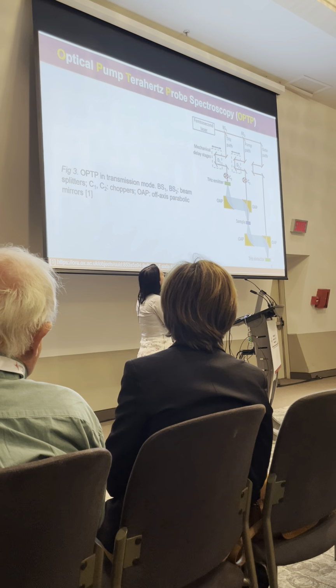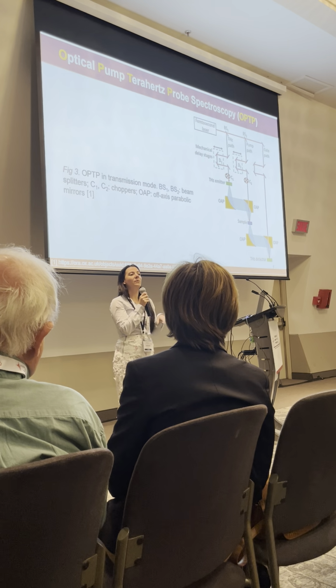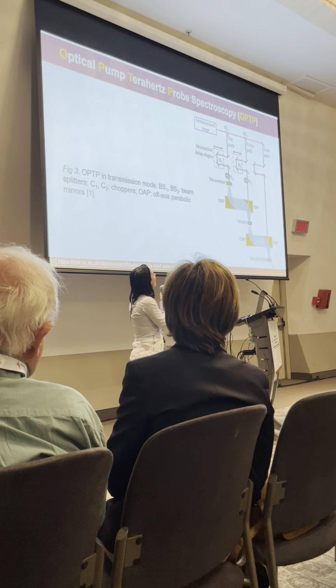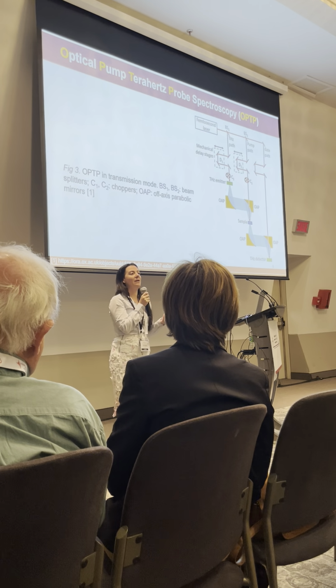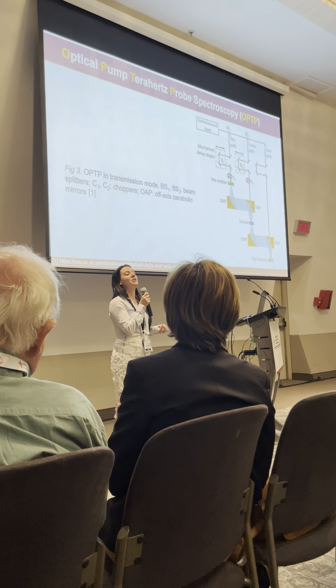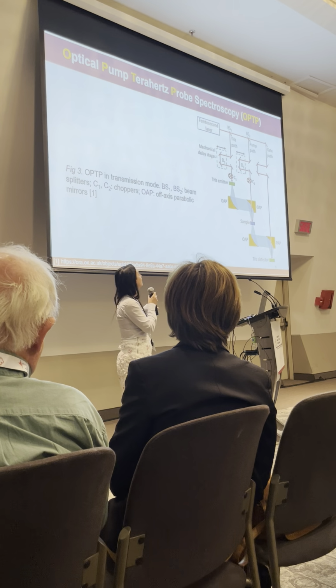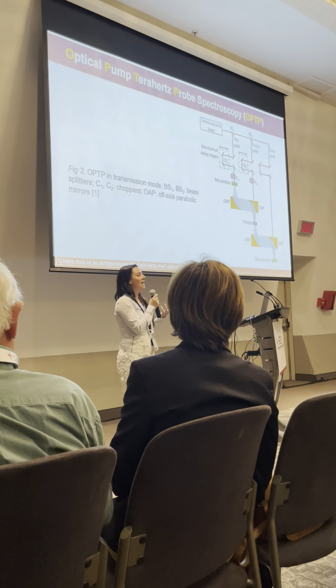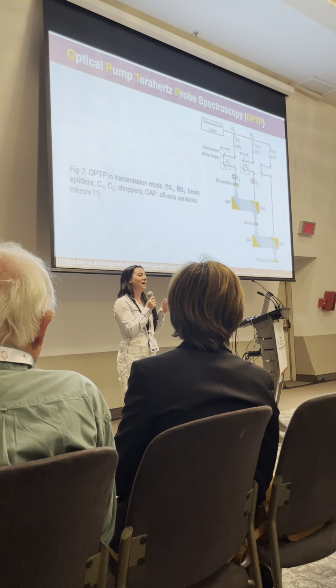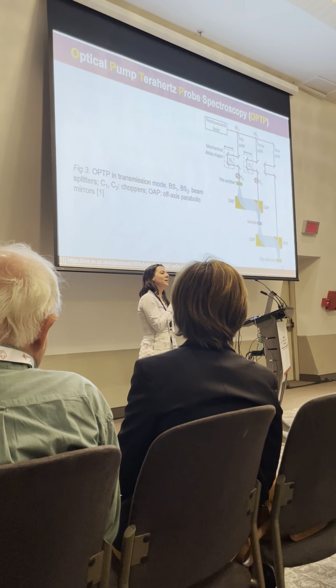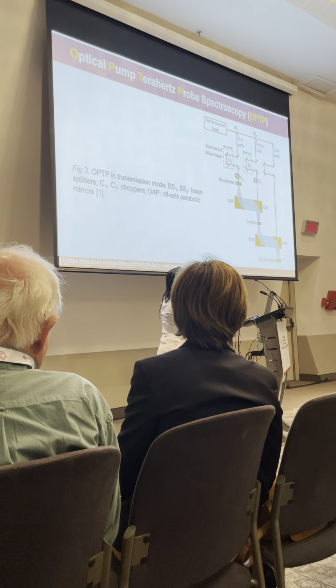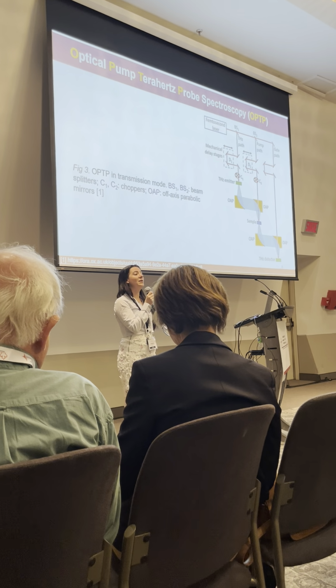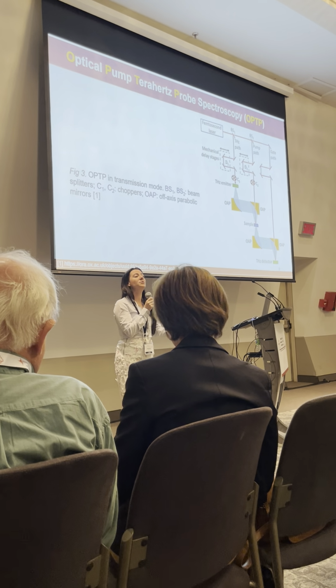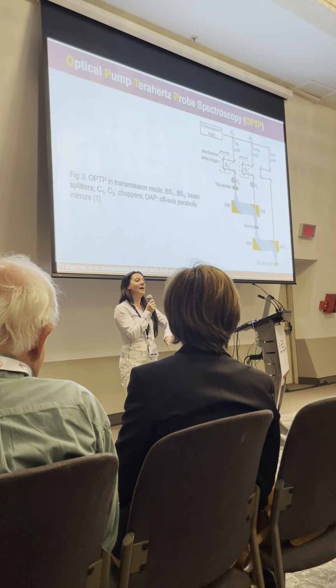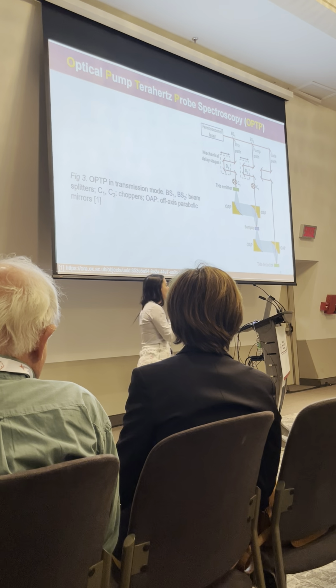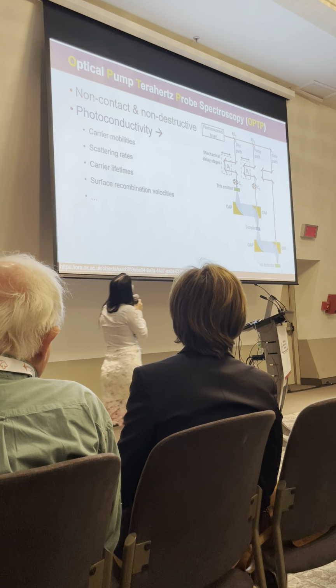So we have an optical pump beam that's usually on the order of near infrared, so 800 nanometers, and then we're measuring the transmitted terahertz radiation and using electro-optic sampling to detect that transmitted beam. This actually was a little bit of a problem because of that indium phosphide substrate. We couldn't get a sufficient terahertz transmission through this. So if we wanted to look at it in that geometry, which is the same geometry that's going to go in the solar cell, we're going to have to switch away from being in transmission mode towards reflection mode.